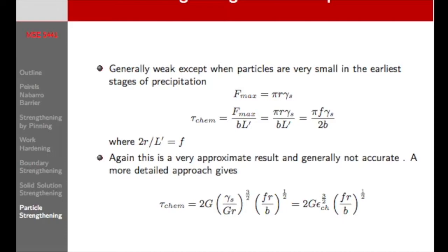The same thing here: if I make very small particles, tens or hundreds of atoms, it's almost all surface. So cutting through that adds a shear offset, and that can add a significant amount. Once the particles approach micron size, this effect essentially washes out because you're adding such a small amount of surface area.